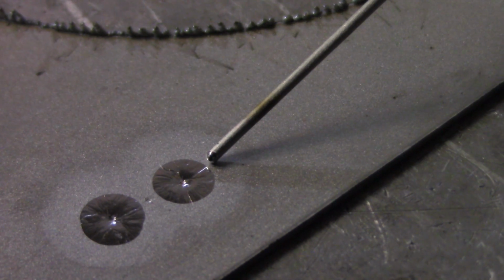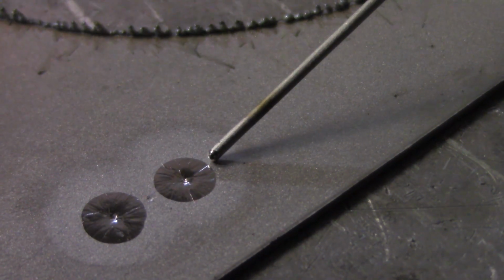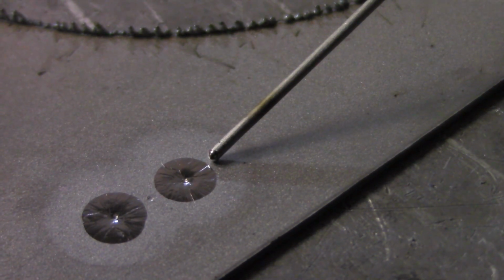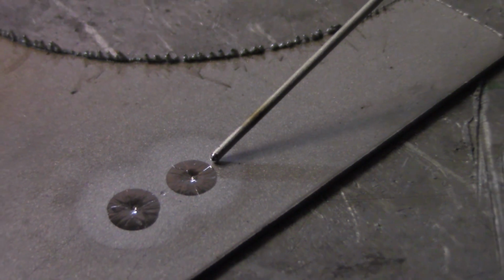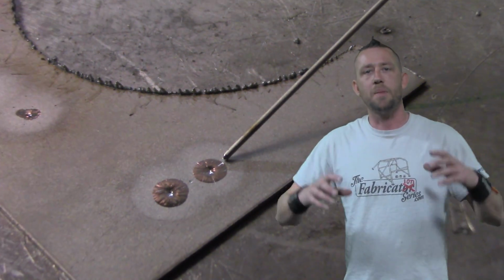Now, one last thing to note about titanium when it comes to welding is that titanium is often known as sticky when welding it, and this is the best way that I can show you how. Now, notice as I get the base metal up to temp here, I'm going to get the filler rod close to the puddle, and while it looks like it was a successful bond, let's take a closer look. The filler metal actually started melting away before it was introduced to the puddle, which made it stick essentially to the base metal. Now the best way to avoid rod sticking is by practicing.